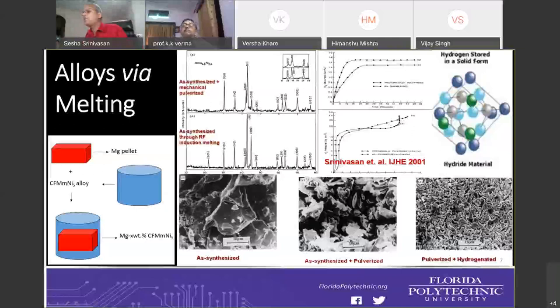What you see is whenever you make a material alloy, it could be a bulk material, but you can also pulverize it and hydrogenate it. Therefore, you can create a lot of pores and cracks so that you can store hydrogen. So that's the material modification we did.